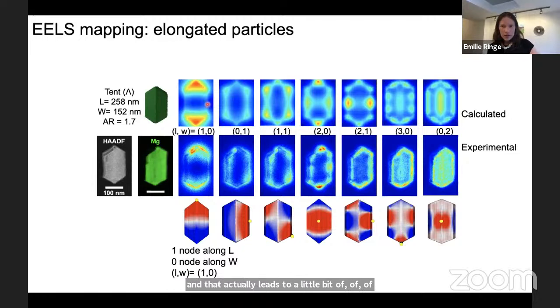In these modes, there's less symmetry in the particles, so we expect less symmetry in the modes, and they become non-degenerate. For instance, the dipole mode leads to a longitudinal dipole as well as a transverse dipole that are no longer the same energy. The quadrupole is still there, and so on. So we're seeing a much richer set of modes as we break the symmetry of these particles.